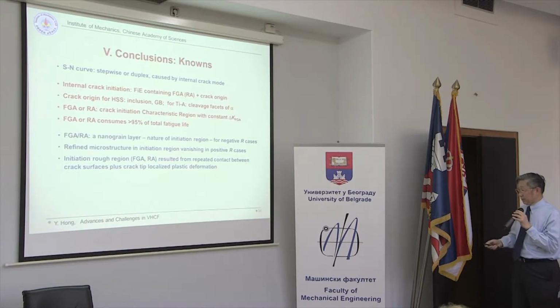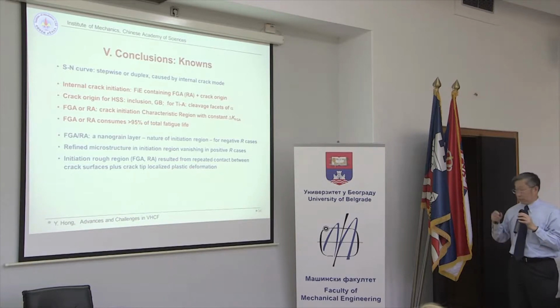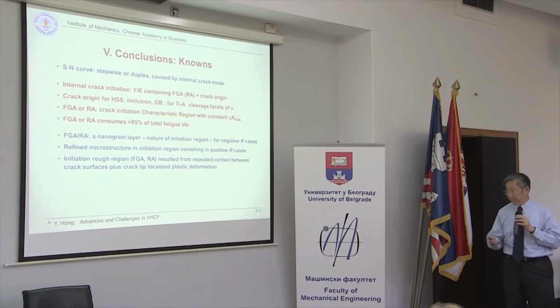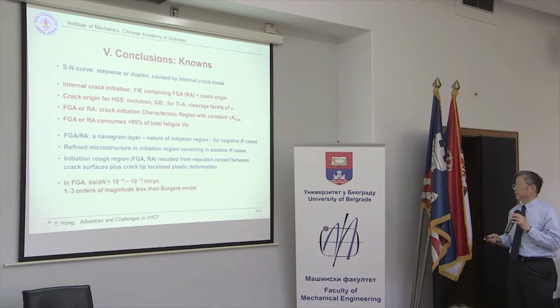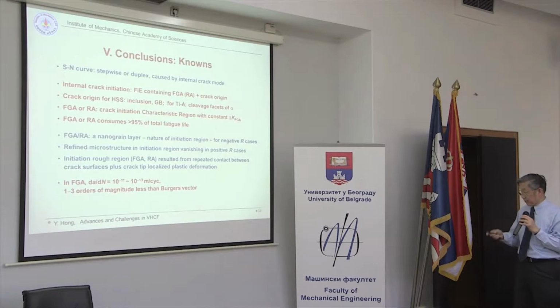And we consider that this region of crack initiation is due to the repeated contact with crack surfaces. And also the crack growth rate is very, very slow.